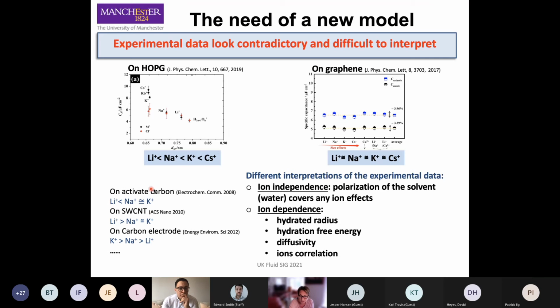And there are many other results in the literature on carbon nanotubes as well, activated carbon and generic carbon electrodes. And then there are different explanations to justify ion specificity and no ion specificity. In this case, the explanation is that basically the water polarizes the surface and covers any ion effects. In this case, instead, there is a relationship between the size of the ions, that was the explanation given in this paper, with the capacitance, so with the adsorption.